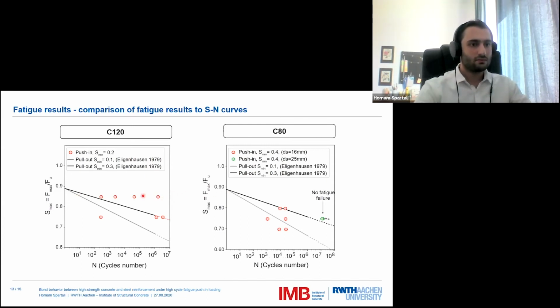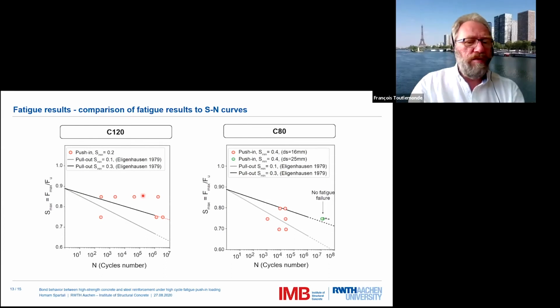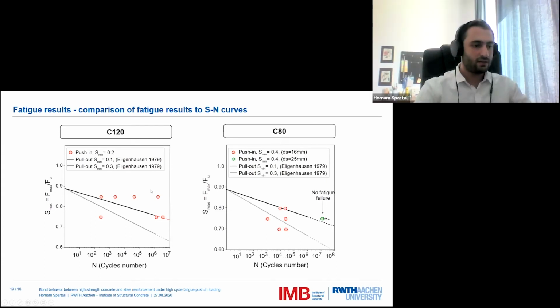Okay. So I have one short question. What was the loading frequency for the fatigue tests? Yeah, it was 5 hertz in all of the experiments, except one, which is this one. This one took, like I said, more than 12 million load cycles. So we applied, as I remember, 2 million load cycles at 5 hertz, and then we increased the frequency to 10 hertz for the rest of the experiment. So it would not last weeks.